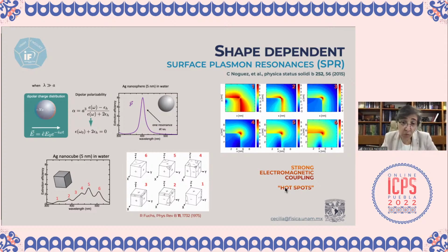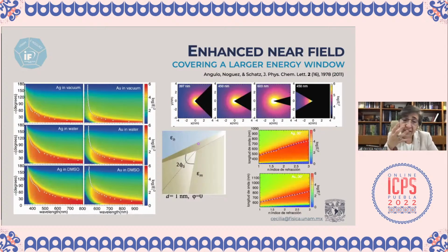Okay, and we can increase up to 6 orders of magnitude the intensity of the electromagnetic field in this way. So this is very nice because, for example, it has been proposed to use these plasmonic nanoparticles, like silver or gold, which are the most common, to capture the energy from light from the sun. And as I told you, systems with shapes like these stars, with some small angles, can cover a large window of energies or wavelengths.